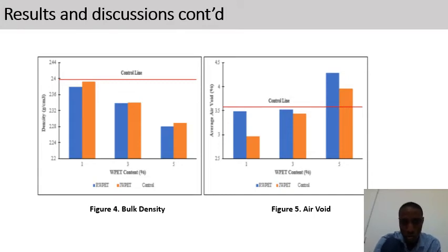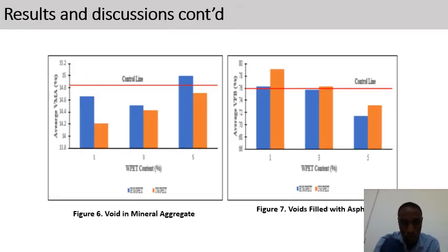Also, the air void increases with increase in the content of this PET. This can be attributed to the elastic deformation of the plastic when used to replace conventional aggregate, which elastic deformation occurs under compaction effort. The next figure is the effect of this PET on the VMA and VFB, which are part of the void analysis.